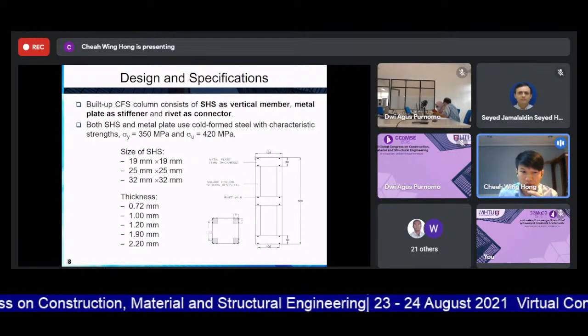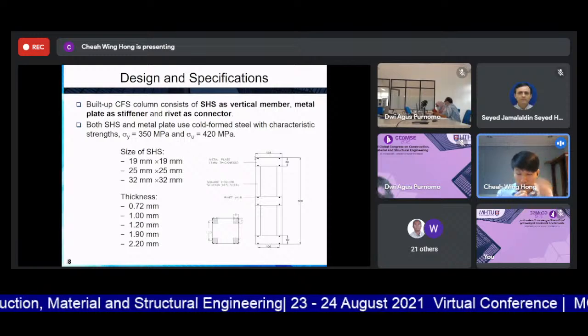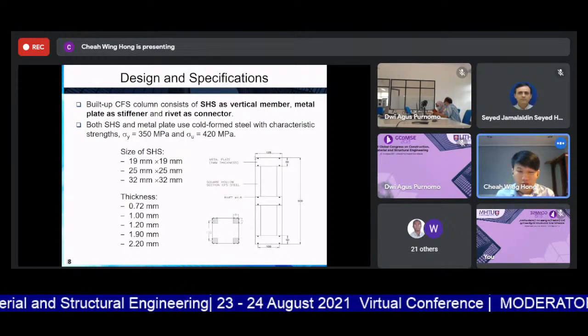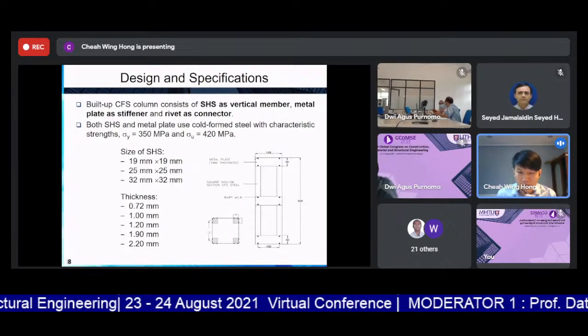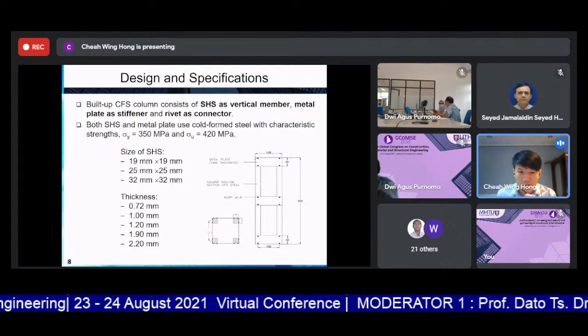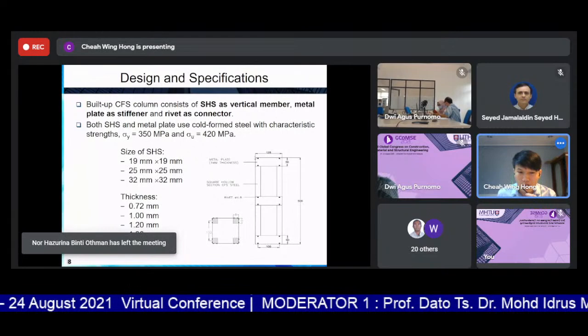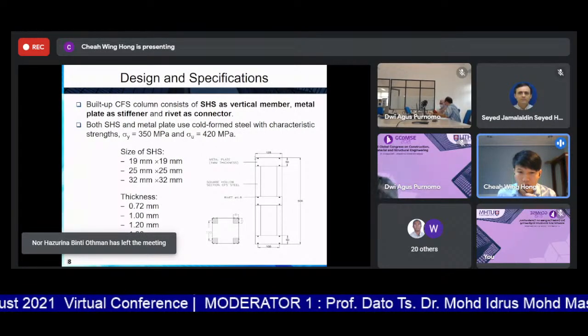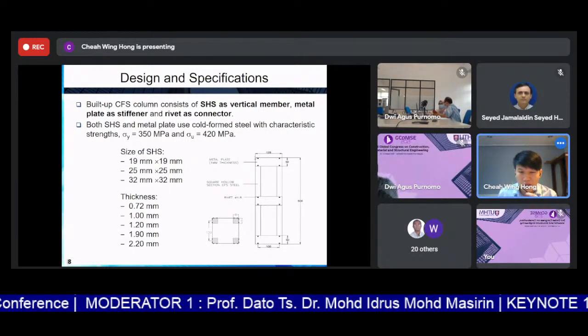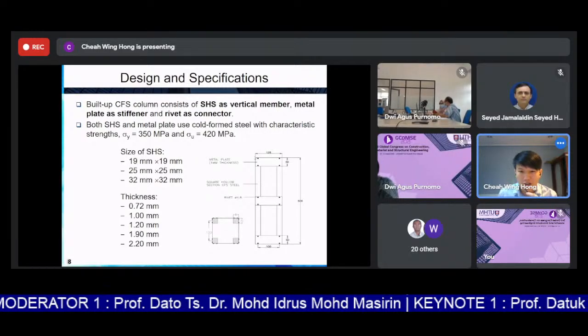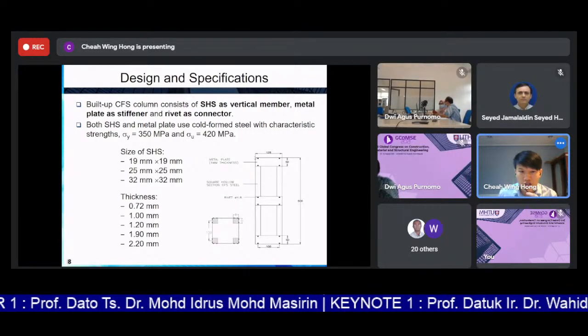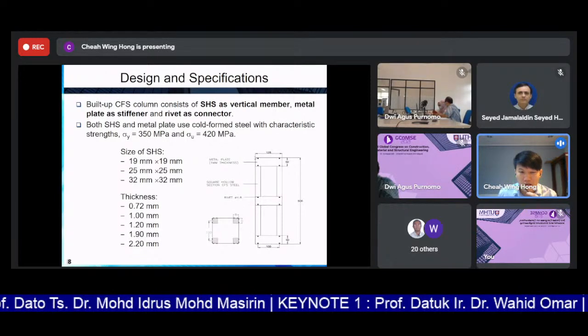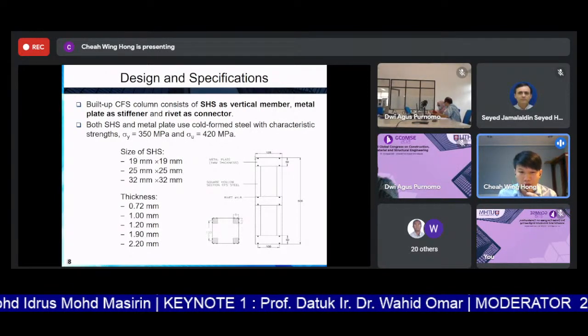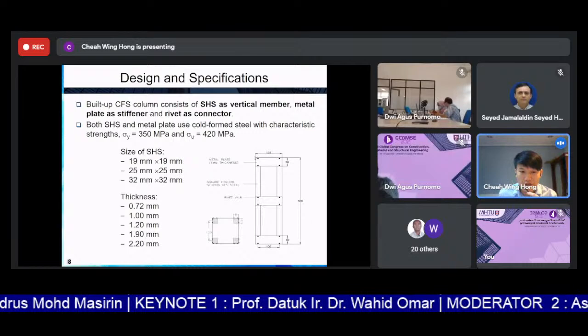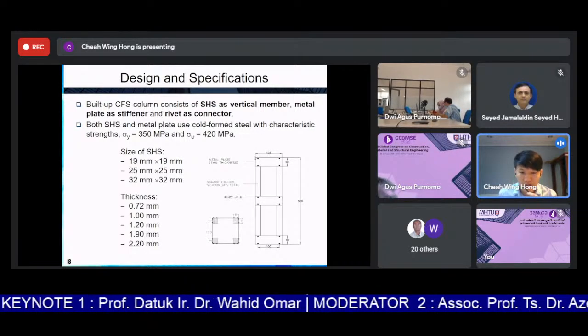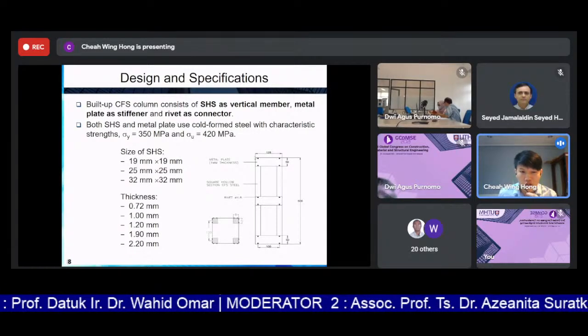So basically, the size of the SHS will be comprised of 3 different sizes: 19 mm times 19 mm, 25 mm times 25 mm, and 32 mm times 32 mm. The SHS used has a yield strength of 350 megapascal and an ultimate strength of 420 megapascal. It will be using 5 different thicknesses as stated below. However, we should note that the thickness of the cold-form steel shall not exceed 3 mm.